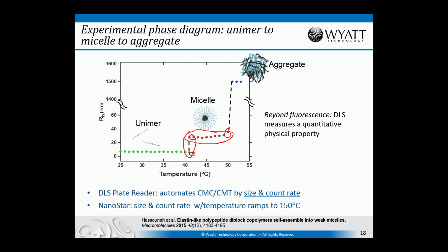By automating this in the dynamic light scattering plate reader, under a series of conditions and concentrations, you could immediately determine the CMC, the critical micelle concentration, and the critical micelle temperature, and you can use two different measurements at the same time. You can see the change in size associated with RH, and you can see the change in molecular weight associated with the count rate. By comparing those, you can get a deeper indication of what is actually happening to your system as it goes through these transitions.